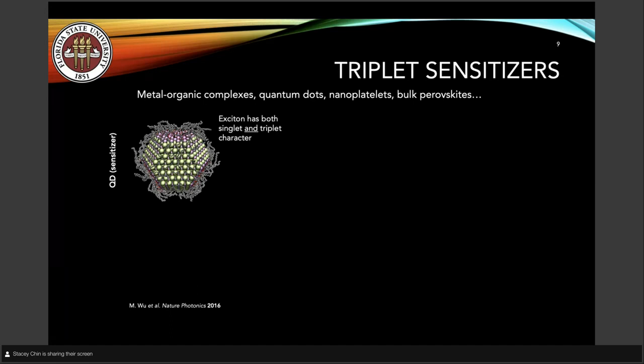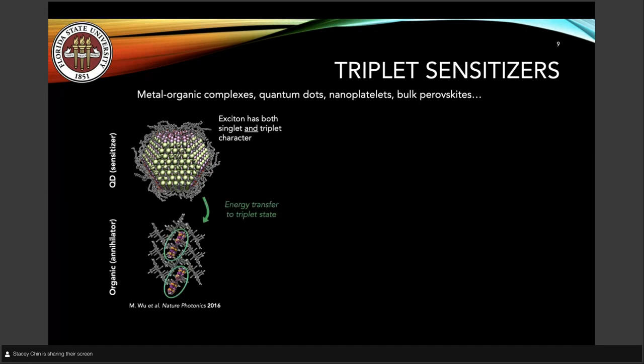More recently, quantum dots were used, and nanoplatelets or bulk perovskites. The quantum dot has the benefit that its exciton has both singlet and triplet character. That means you can easily do energy transfer from this exciton to the triplet state of whatever organic material you're using. And then once the energy is in the triplet state, it can undergo triplet-triplet annihilation and create your higher energy singlet state.